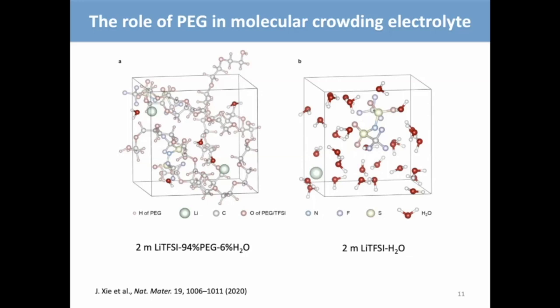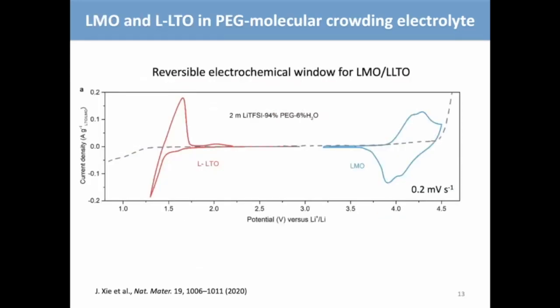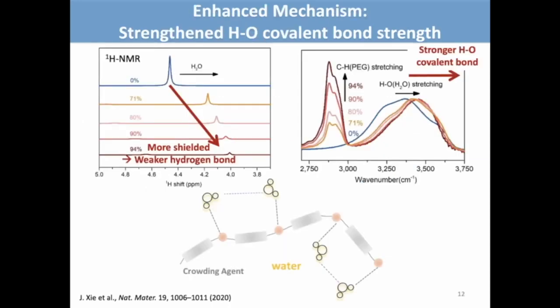So you can see in the regular aqueous electrolyte, we have a lot of free water running around, and with the molecular crowding electrolyte, not only are we reducing the free water, but also the waters are actually bound with the PEG molecular crowding agents. And therefore their environments are very different in terms of their property and their chemical environments.